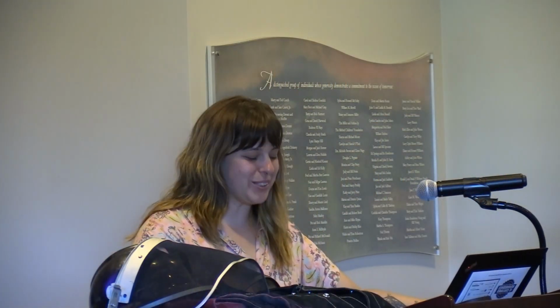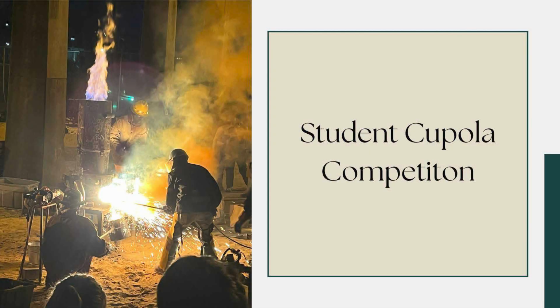Oh no. So during the competition, we were unable to get the iron out of the furnace. So what had happened is that we had gotten a bridge in the tap hole, which just means that iron has solidified, blocking any exit route for the molten metal inside. So that means that we had to get an oxygen lance, pictured here, which is very exciting, but also terrifying. It's pressurized oxygen that's able to cut through thick metal, and the heat is just very concentrated. And so they needed to do that. That also did not go well. I don't know what was going on with their oxygen lance. But we were able to get metal out 3 times, so that was great. But we had a lot of problems that kind of contributed to this.